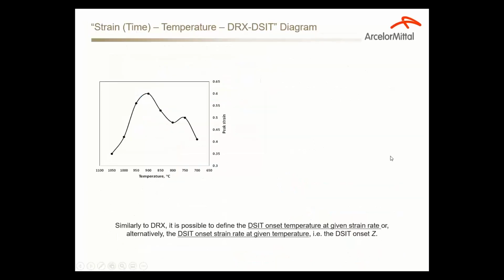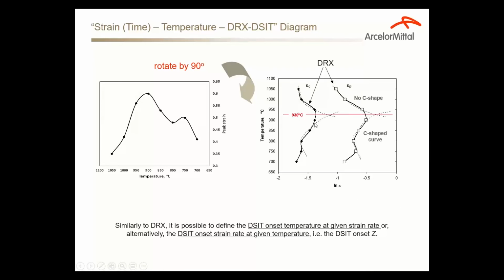And we actually did this. We took the graph of the fixed strain, rotated it by 90 degrees, and we obtained this kind of curves, which resemble the CCT, the TTT, I'm sorry, curves of conventional phase transformation. So using this kind of graphs, we can separate dynamic recrystallization from the phase transformation. We can determine the temperature at which the transition is happening, and the controlling mechanisms.